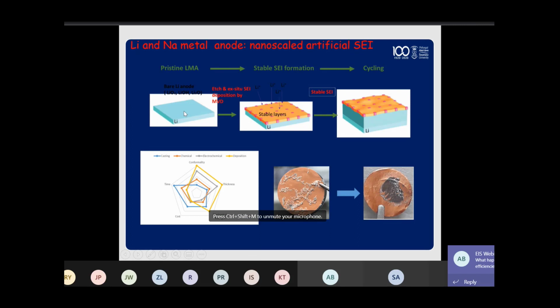So what we do, we deposit a nanoscale artificial SEI layer on top of the lithium metal. This is artificial, so we decide the composition, and we make sure that it's also mechanically stable. Therefore, it has to be, of course, ionically conductive, and the lithium can shuffle in and out of this stable layer. And of course, you can plate and strip, so it can go from lithium plus to lithium zero and vice versa, throughout, without breaking and without modifying the solid electrolyte interface.